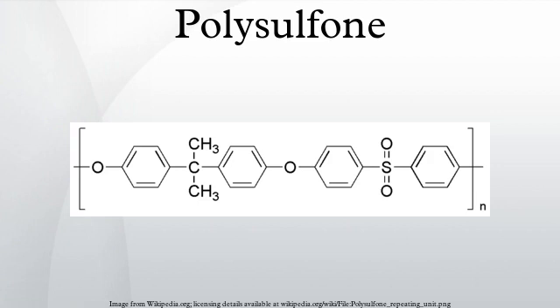Polysulfon allows easy manufacturing of membranes with reproducible properties and controllable pore sizes down to 40 nanometers. Such membranes can be used in applications like haemodialysis, wastewater recovery, food and beverage processing, and gas separation. These polymers are also used in the automotive and electronic industries. Filter cartridges made from polysulfon membranes offer extremely high flow rates at very low differential pressures when compared with nylon or polypropylene media.